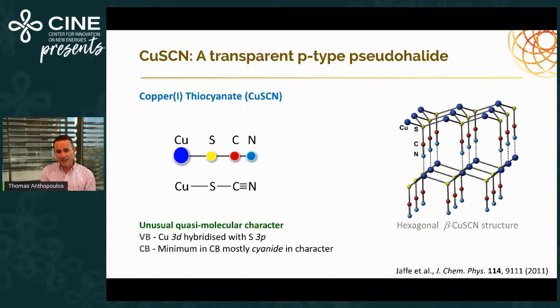It's a quasi-molecular system, essentially, and has a mixed character where it comes down to the energetics. So the valence band is dominated by the copper 3d orbitals hybridized with the sulfur, and essentially it's a layered system. And the conduction band minimum is actually mostly dominated by the cyanide character. Therefore, there is a huge asymmetry in the charge transport, but also in the character of it.